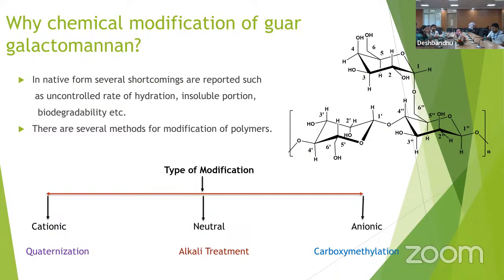Now, why the chemical modification of galactomannan, guar galactomannan? The modification is opted for to target two properties: the first, to introduce the desired characteristics, and the second, to overcome the undesired ones. It is a natural polymer, and there are several undesired characteristics like uncontrolled rate of hydration, insoluble impurity, biodegradability, etc. There are numerous methods for chemical modification, but based on the group introduced, broadly, the modification is categorized in three categories: the cationic modification, the anionic modification, and the neutral. For this study, I have carried out the cationization via quaternization, anionic modification by carboxymethylation, and the neutral treatment was simple alkali.